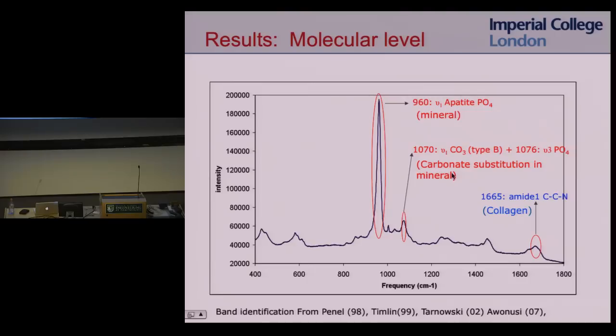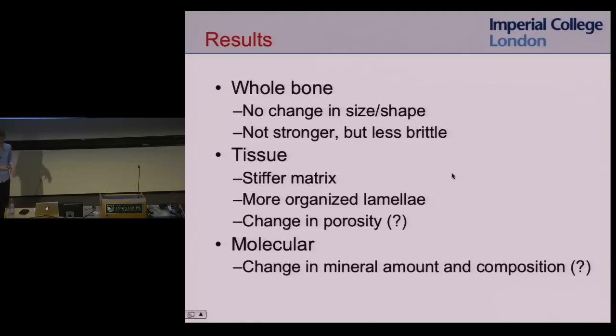We can also do a multivariate analysis, which takes the spectrum as a whole, and using principal component analysis, then try to understand how the entire spectrum varies as a whole between the two groups. And so skipping to what we've found, we could detect a change in the mineral amount and composition. So even though we know that the collagen is changing, what we can measure is a change in the mineral. And that's not too surprising because the collagen and mineral are very tightly related. The collagen provides a template for the mineral to lay down on. It's not surprising that if you change that template, you're going to change the mineral.